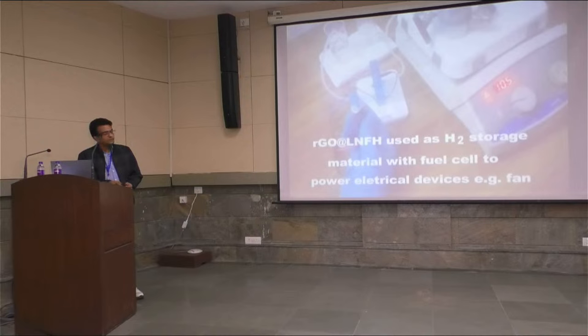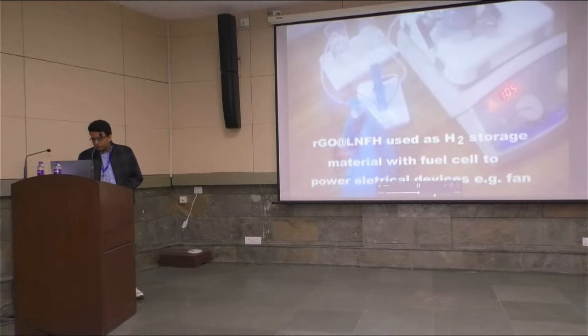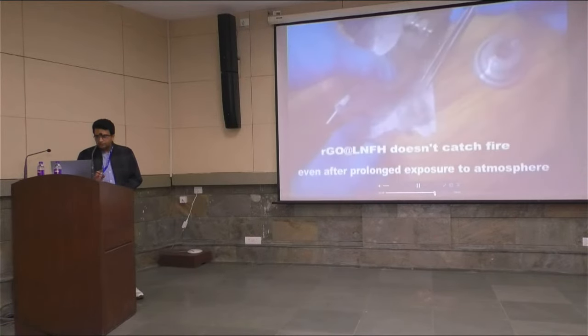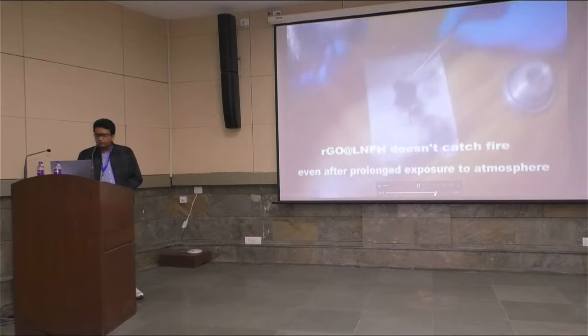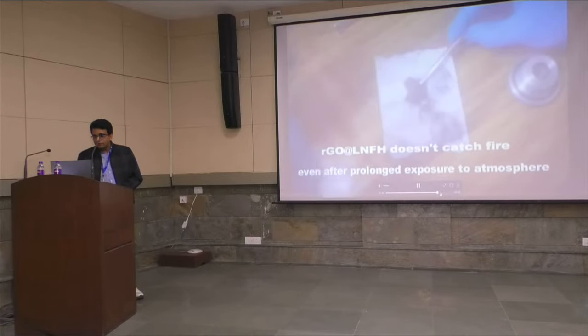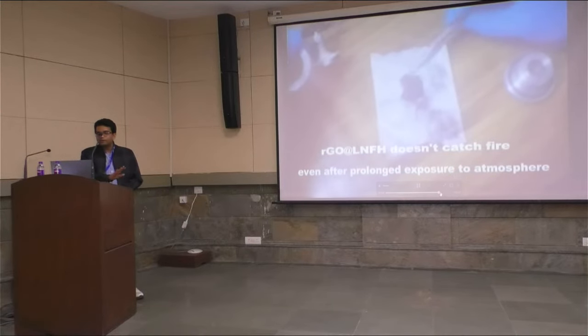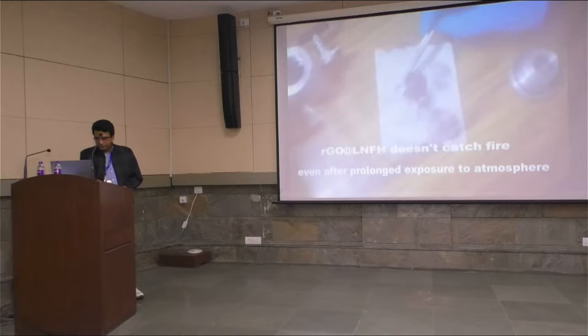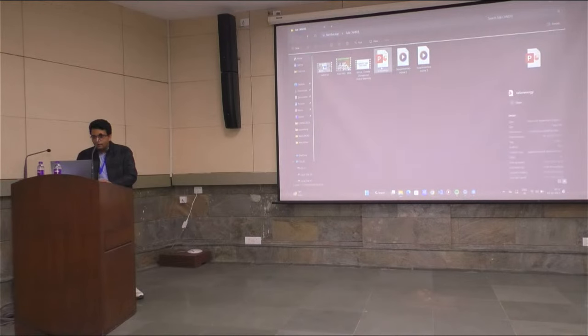When we have used this hydride in the fuel cell, and once we take it out, generally it catches fire, but when we decorate this hydride with graphene, it does not catch fire. We have left the hydride for around 5 to 6 months and it does not catch fire. I am not showing you the other video due to scarcity of time, which indicates that the hydride does not catch fire when we covered it with the graphene. Now, I am summarizing it in 2 minutes.